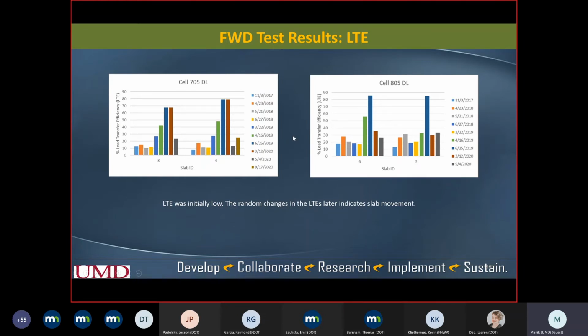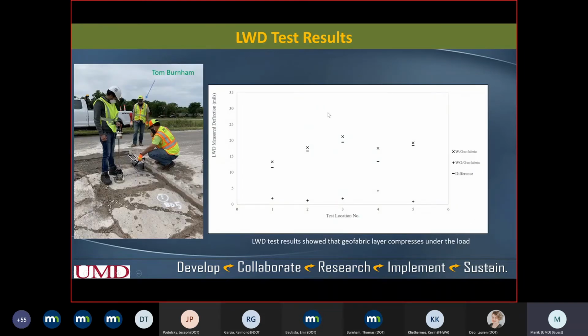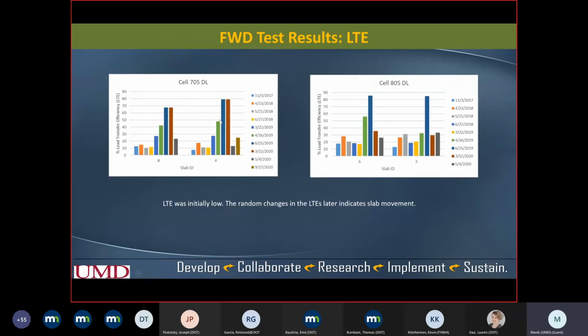I'm not sure, but it looks like the slabs kept moving on this geofabric layer, and that's why LTE depends on the crack width. I think that probably has a role to play. Also, the lower LTE initially is probably because the geofabric layer could absorb a good amount of load, I would say. That probably also resulted in low load transfer efficiency in the beginning.